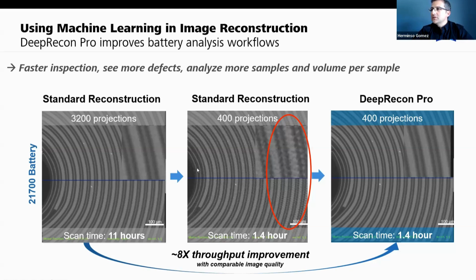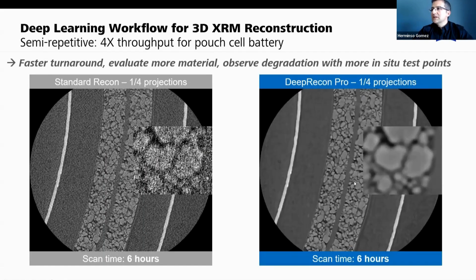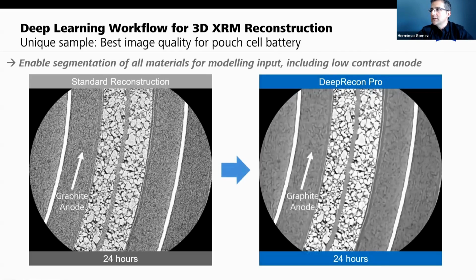When you use Deep Recon, because you have a model that can identify what is noise from actual data, you can recover the data with fewer projections and get faster throughput, scan time, because you're collecting fewer projections. If you do a very long scan and you don't care about the number of projections, you still can get improvement from noisy data to very clean data that gets rid of the noise and allows you to use segmentation software that gives you an idea of the pore network, and even identify some of the low density features in here to do your simulations, if you want to do some type of simulation.